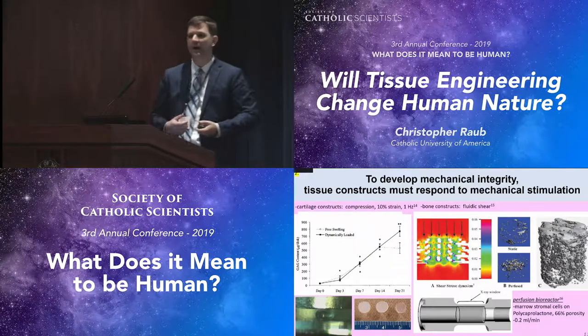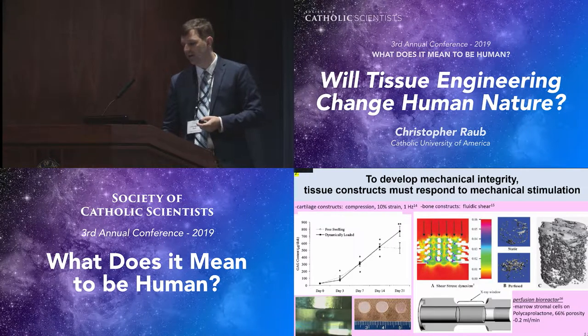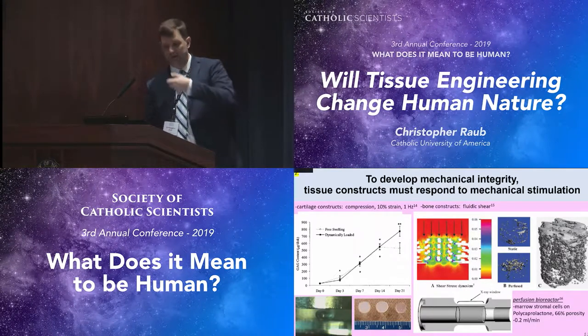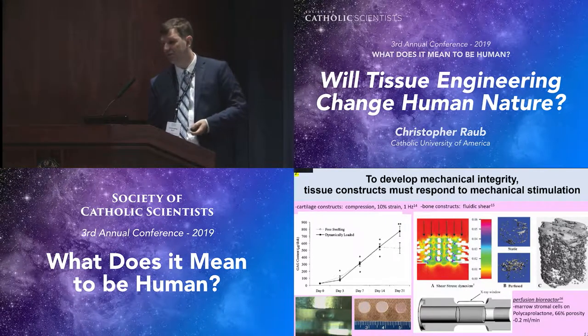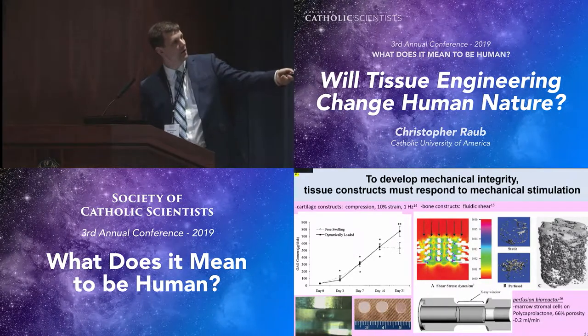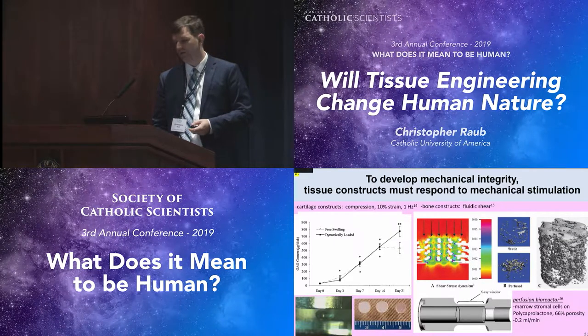And that opacity derives from the extra molecules that the chondrocytes have deposited in the extracellular matrix. Similarly, bone, when you load that mechanically, when you're walking or moving, has tiny networks of pores through them which exert shear on the resident bone cells. And to recapitulate that in a bioreactor, you can have a perfusion setup where you put marrow stromal cells that will differentiate into bone-like cells on a substrate that's porous, in this case about 66% porosity. You can see here from the model that shear stress should be imposed by the flow rates that they put in the perfusion bioreactor, and indeed, those cells were able to deposit more mineral, indicative of new bone formation, in the perfused versus the static culture.